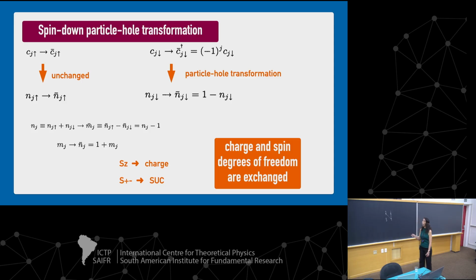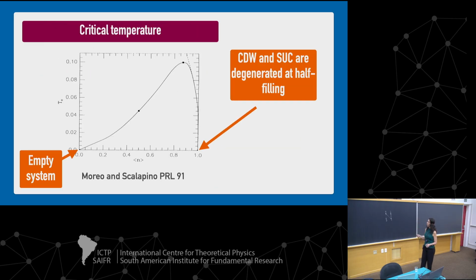And if you go on and follow these calculations once again, and see what happens in the spin-spin correlation functions, we see we map the Z component of the spin into the charge correlation functions, and the up and down spin correlations into the superconductivity order parameter. So the charge and spin degrees of freedom are exchanged in these cases. So this is why this has been known for a while.